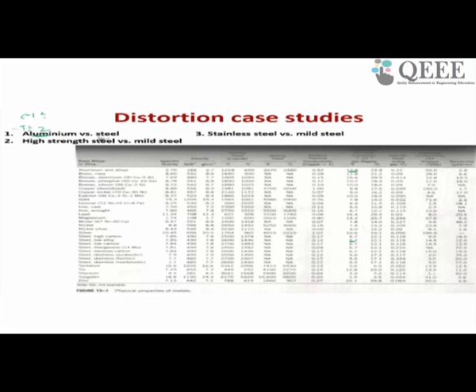So if you see aluminum and steel, in two cases aluminum is better. For example, from the coefficient of thermal expansion point of view, steel is better, and from the Young's modulus point of view, steel is better. However, from the yield strength point of view, aluminum is better, and from the thermal conductivity point of view, aluminum is better. So two cases each. So distortion and residual stress will be a smaller fraction, that can be possible. Similarly, you can do analysis for other combinations.